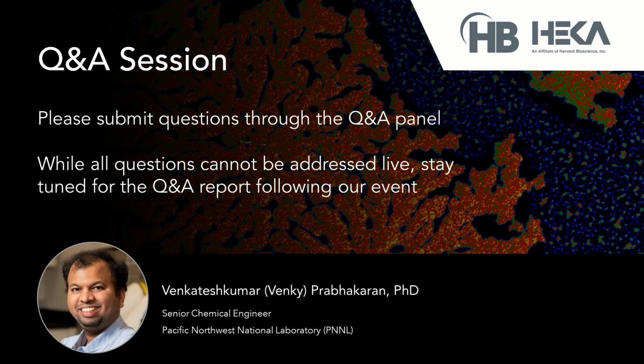In aqueous electrolyte it's not quite possible because you typically have a high evaporation rate. But in a non-aqueous electrolyte, if the electrolyte is stable, one could try in a controlled environment. For those applications, you may need to put the entire setup inside a nitrogen or other environment to keep the tip stable. Otherwise, you will have a lot of evaporation that creates a bubble and blocks the measurement.